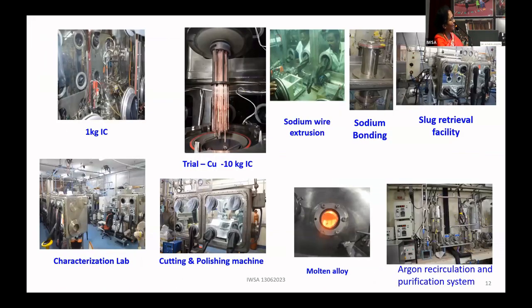And next, we show the entire system. The 1 kg injection casting, all the trial runs are done using copper. And we have one more 10 kg system also. Sodium wire extrusion, sodium bonding. You have a slug retrieval facility. The characterization lab for the non-metallic impurities. Cutting and polishing machine inside the glove box, everything. Then you can see the molten alloy, how it looks at 1450 degrees centigrade, and all the system needs to be under high purity argon. So you require an argon recirculation and purification system. The ppm level of oxygen needs to be less than 20 ppm.